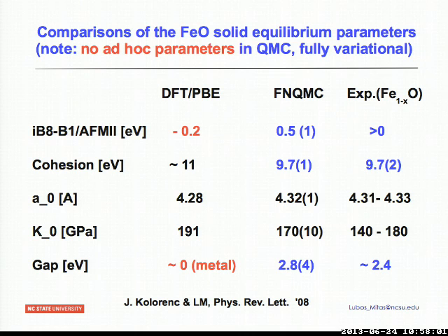Basically, you take the top valence electron and you put it, say, somewhere in the conduction band into a particle state. You get another total energy, you calculate it, you subtract the two energies, and you get a gap, very much like in nature. So there are no one particle values here, no one particle eigenvalues, nothing like that. You really do what nature does. It knows only one energy, and that's the total energy. You have one, you hit it, you go into the excited state, exactly in here.